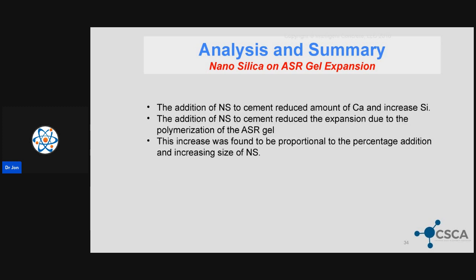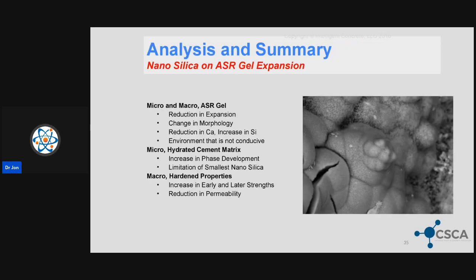The bullet points and the key takeaways from this were that the addition of nanosilica to cement reduced the amount of calcium and increased the amount of silica. The addition of nanosilica to cement reduced the expansion due to the polymerization change, the morphology that we looked at of the ASR gel. And the increase was found to be proportional to the percent addition and increasing the size of nanosilica. So the more that you added and the larger it got, the better the resiliency to ASR gel expansion.